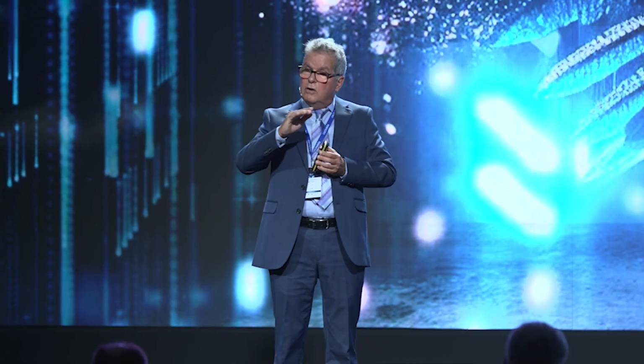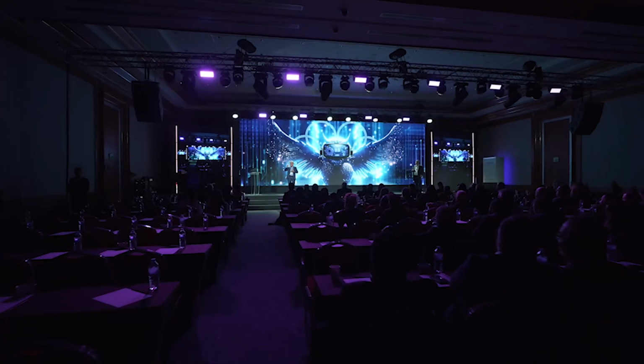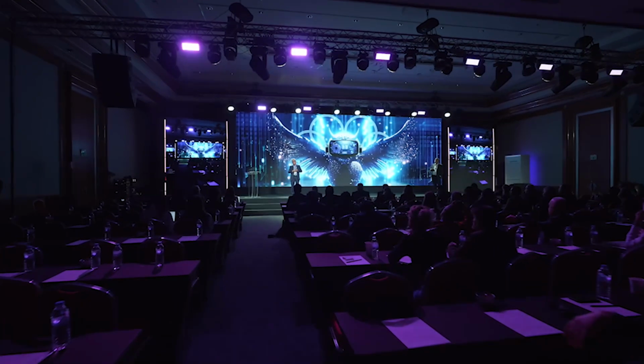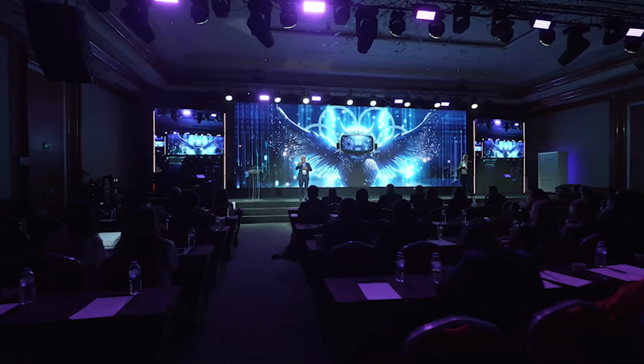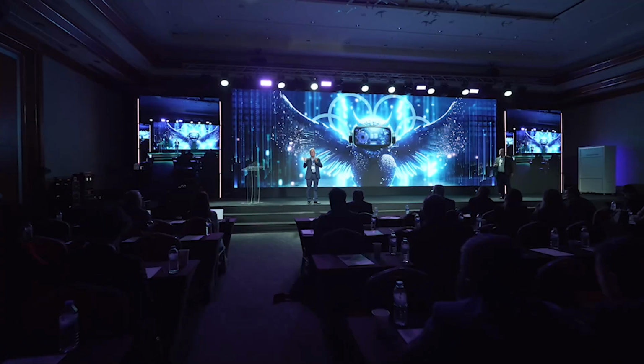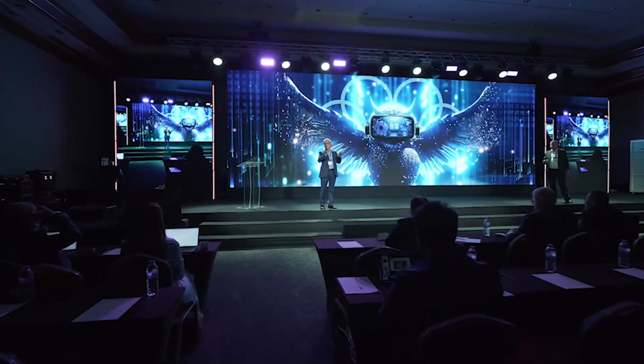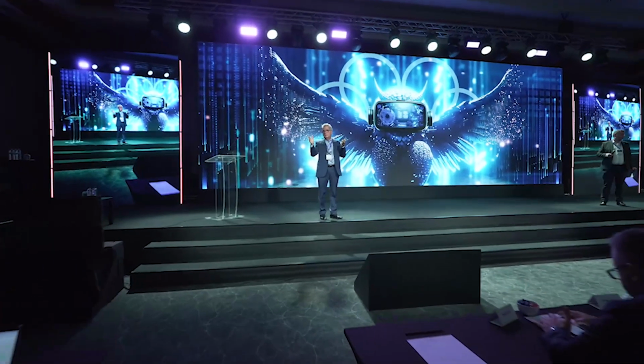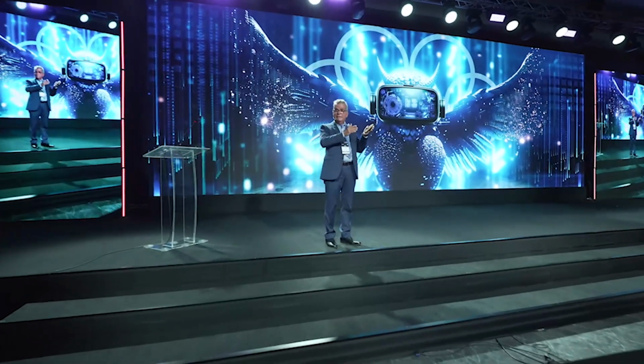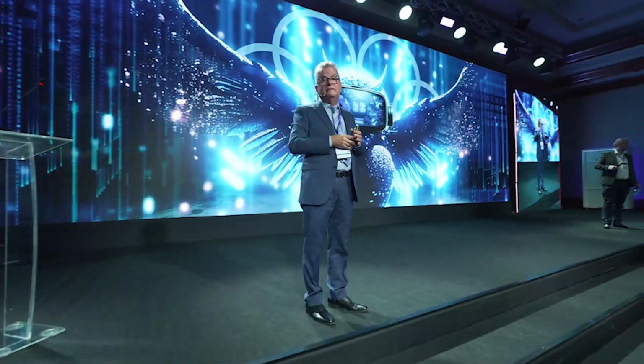So it's a very good cost when you compare it to the cost of clinker, which is between 35 and 45 US dollars per ton. But again, this is not a rule. It depends on the royalty cost, on the technology you're using, on the local context, the cost of transportation, and everything. But more or less, the cost of calcined clay ranges between 15 and 25 US dollars per ton. Worst case scenario, 25. Best case scenario, 15 US dollars per ton, more or less. Thank you very much.